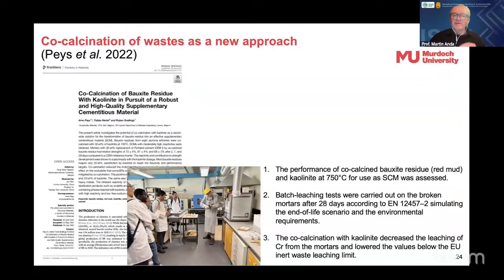And so what we found is that we can actually co-calcine this red mud and kaolin at 750 degrees C, and it can be used as an SCM or a geopolymer thereafter.